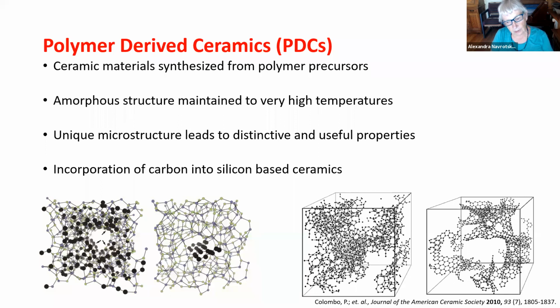The silica-rich network contains some carbon, and I'll come back to that. The carbon-rich network probably contains mostly carbon, and the carbon-rich network one can think of as distorted graphene-like sheets of a few layers in thickness. They are not planar, they're distorted, they interact with the silica-rich part at their edges, but still they are primarily carbon-based materials. The silica-rich regions are essentially silica, but there's actual carbon dissolved in it, and the carbon substitutes not for the silicon, because although you can say both carbon and silicon like tetrahedral coordination, the bond lengths are just too different. Carbon is just too small to substitute for silicon, except under some very special ultra high pressure conditions that are not what we're interested in.